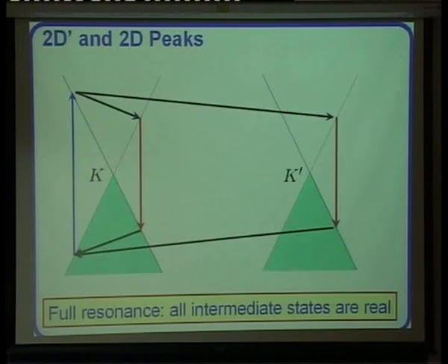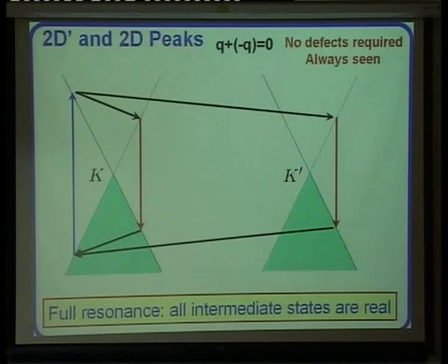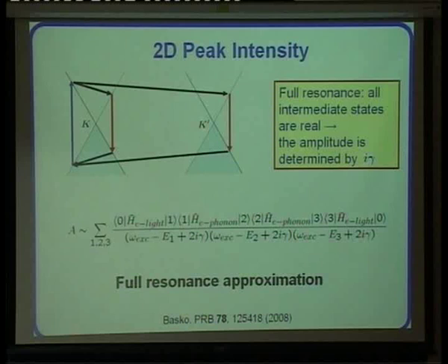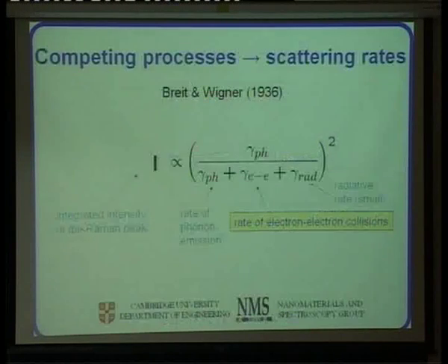And then, of course, we have the 2D peak, and in this case, this is the simple process, and there is a process where all the intermediate states are resonant, and we could, in principle, have a similar situation where all the other states actually contribute. And in fact, it turns out that in this case the full resonance approximation, so only considering the most resonant of the terms, is actually good. So there's no surprise there, unlike what happened in the G-peak, even though the full resonance approximation that has been used since 2008 is not, strictly speaking, correct.